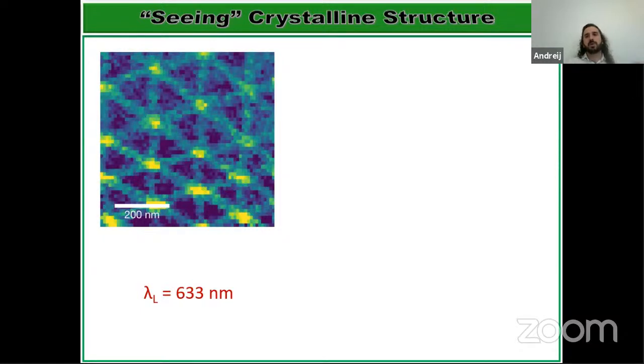But the intensity decrease is frequently observed in near field systems, especially in our case that we do spectroscopy. We record the spectra, which sometimes take a long time, about 1 second each. And so the thermal drifts are unavoidable.